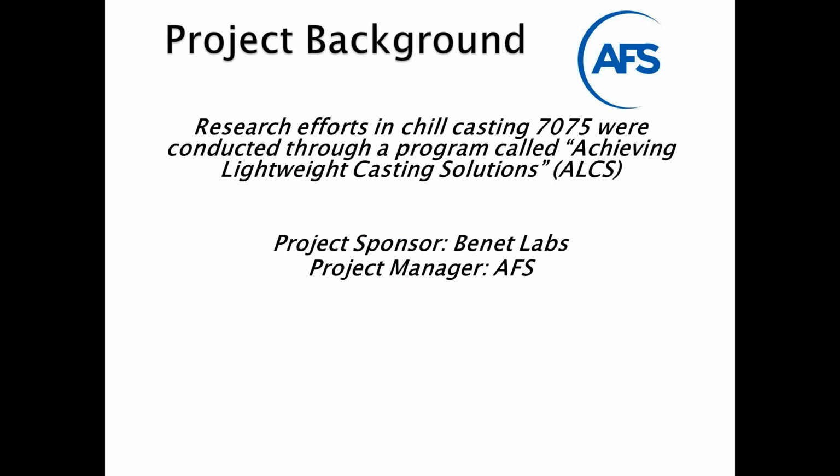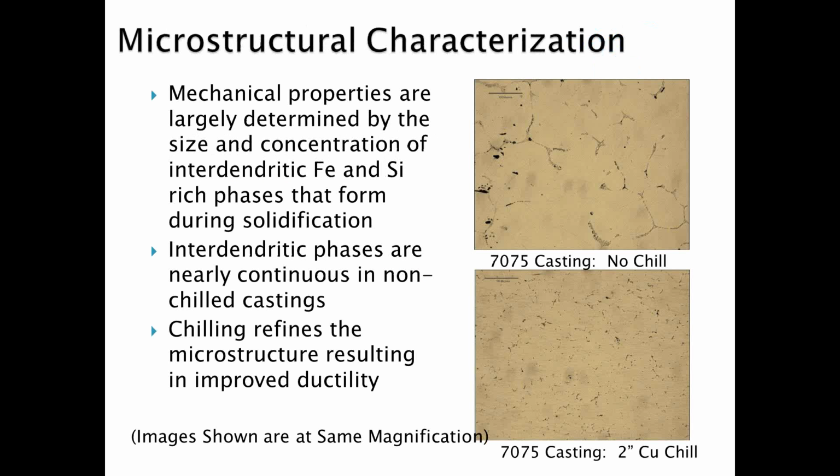So this program was through the American Foundry Society, and really looking at 7075 alloy as part of an Achieving Lightweight Casting Solutions program. The project sponsor was Benet Labs, and as I said, managed through the American Foundry Society. In an alloy like 7075, it turns out that the mechanical properties are controlled by interdendritic iron and silicon phases. That's not particularly surprising, and when you have those phases, your elongation goes down if they're not widely dispersed and separated.